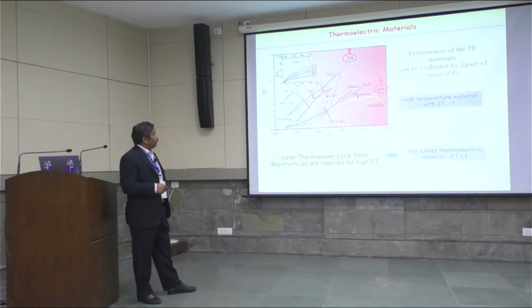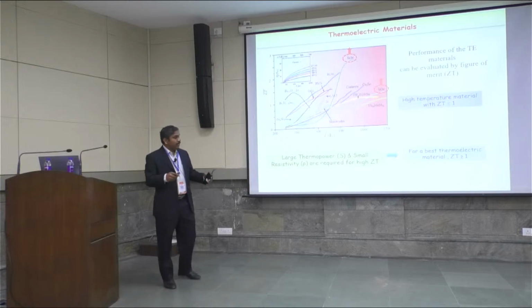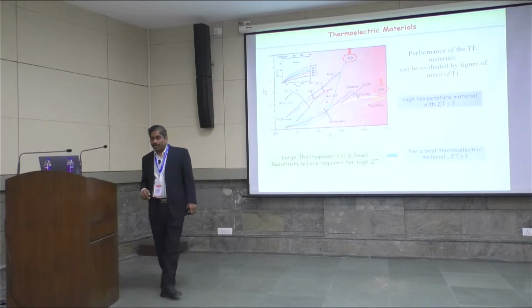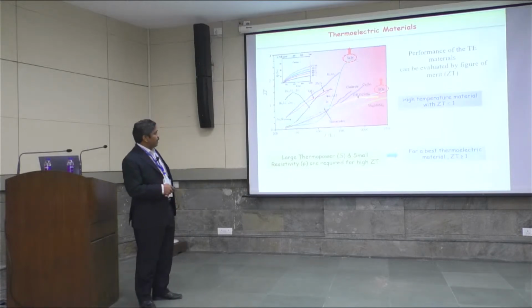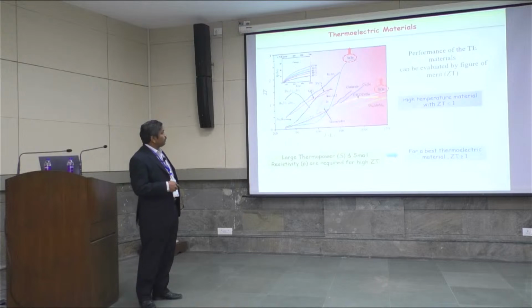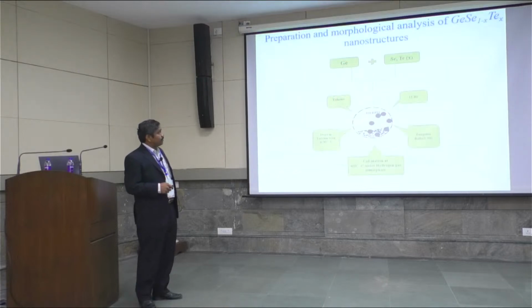Tin selenide has recently evolved as an intermediate temperature material, like tin selenide. It shows a ZT of more than 2.5. And of course, silicon germanium for high temperature. And like that, the scenario of thermoelectric research goes on with nanostructured materials, especially semiconductor materials, trying to improve the transport characteristics.